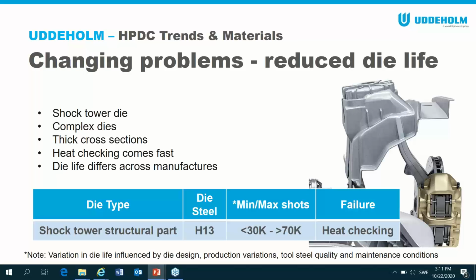So if we look at shock towers, I've seen quite a few of these now in my trips globally. And if you think about a shock tower in itself, they're all different shapes and sizes, but they're quite complex panels. They're quite thick and quite thin in certain areas. Heat checking seems to be the main failure again with these, and it seems to come quite quick on some of them. And the die life there is just like with all the other stuff, depending on which manufacturer you're at. So again, I visited some customers that run shock towers and they can't even get 30,000 shots. In fact, they really struggle. I visited others where I'd probably say a medium average life is about 60 to 70,000 before major issues.